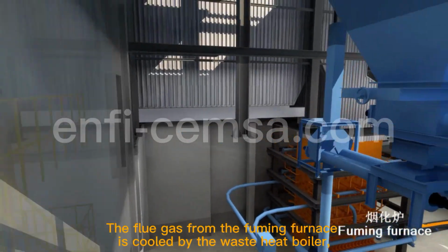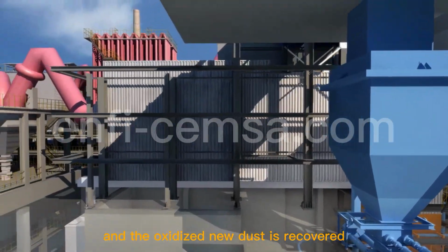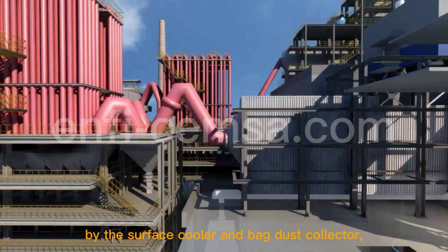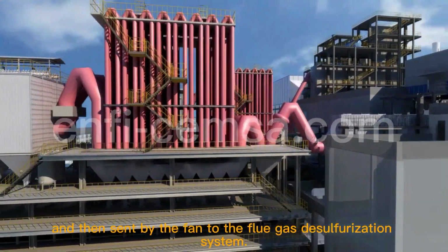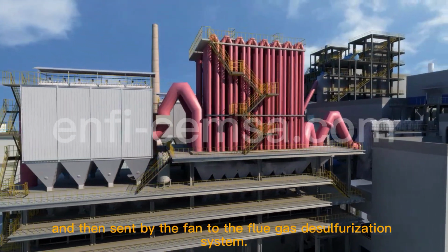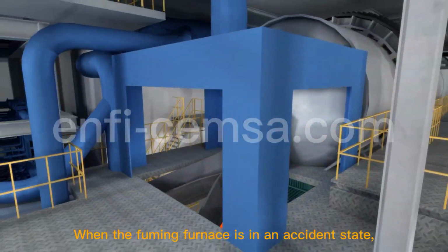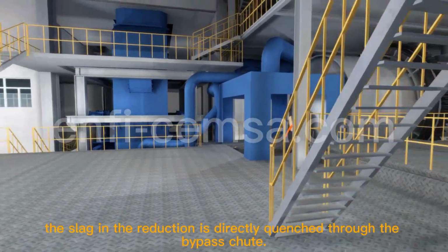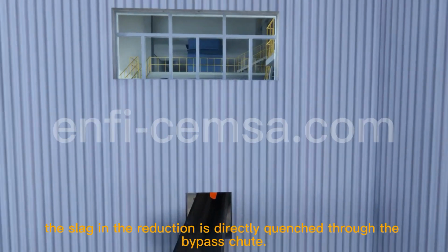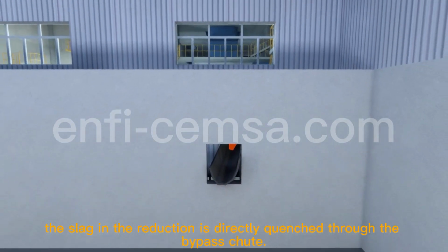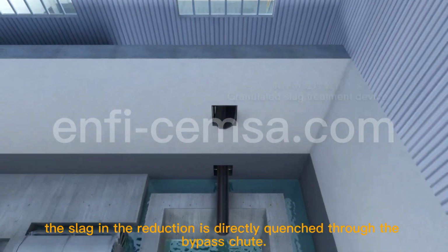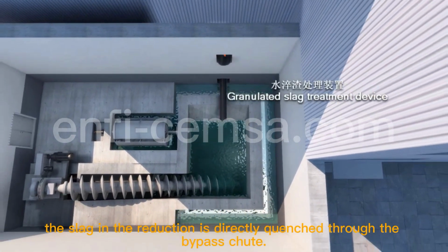The flue gas from the fuming furnace is cooled by the waste heat boiler, and the oxidized zinc dust is recovered by the surface cooler and bag dust collector, and then sent by the fan to the flue gas desulfurization system. When the fuming furnace is in an accident state, the slag from the reduction furnace is directly quenched through the bypass chute.